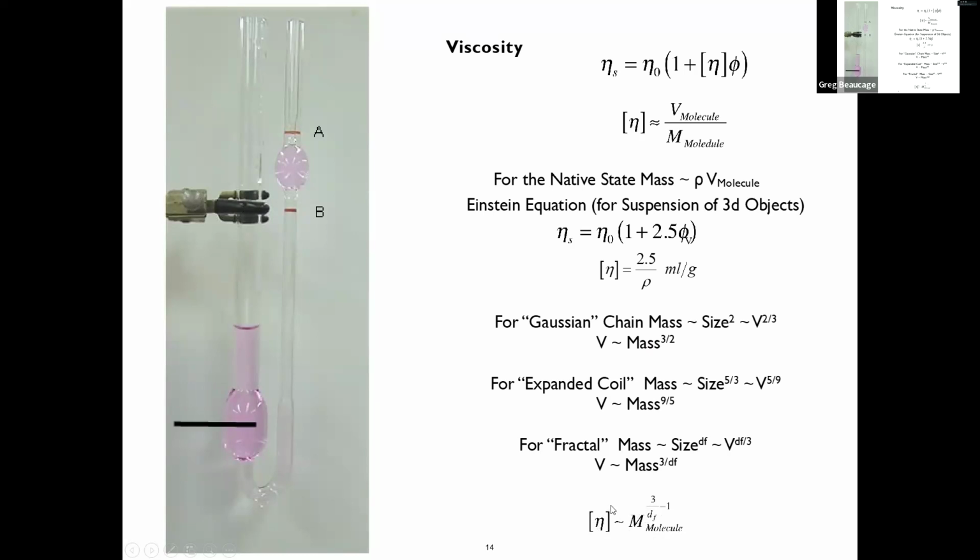So it's higher. So you have number average that you get from osmometry or osmotic pressure. There's the weight average you get from scattering. So that's higher than number average. And then there's this viscosity average, which is higher than those 2. It's the next higher average molecular weight. And the dependence of it is the a dependence. In other words, what moment you're getting is the a moment of the molecular weight. So anyway, those are the 3 standard molecular weights people have: Mn, Mw, Mv, which comes from this thing.